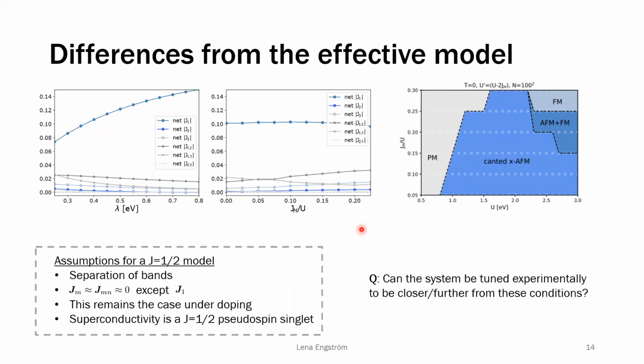But what's interesting is that the extra order parameters that we see are not from these other bands moving closer to the Fermi surface or something like that, but it's the mixing between these different states that becomes larger, sort of indicating that this J1/2 state becomes less of a valid description, just projecting out that.